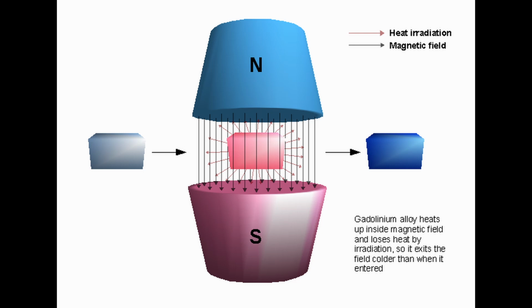That sounds exciting. But even so, it seems like we're still a long way from ditching our regular fridges. The sources mentioned that to replace the current vapor compression tech, we need much better, cheaper, and more abundant materials, and ideally something that works with weaker magnetic fields, maybe even just permanent magnets. We don't want to have to install a giant superconducting magnet just to keep our milk cold, right? Exactly. The Holy Grail is a material with a strong magnetocaloric effect over a wide range of temperatures, and that works with magnetic fields of 2 Tesla or less, something you can get with a good permanent magnet.